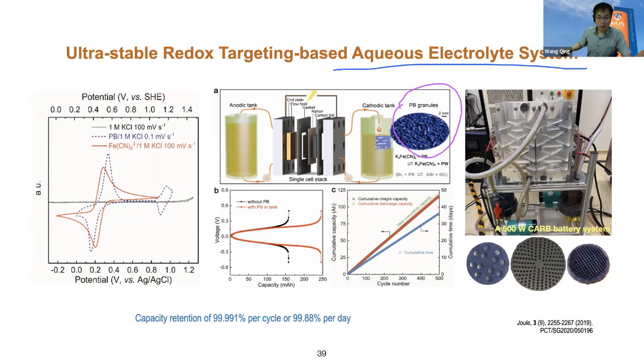I know recently Prussian blue or Prussian blue analog material has been used in conventional batteries, including sodium batteries. But here we just make the Prussian blue into granules like these honeycomb structures. They have pores, so the electrolyte can flow through. So we store this Prussian blue material in a tank, and I use a very stable redox species, ferricyanide. If you study electrochemistry, we know ferricyanide is a very important redox species we use all the time in water-based electrolytes. It's very stable, and it has a decent solubility. So the ferricyanide can react with the Prussian blue for charge and discharge. Then it can make the flow battery much safer.